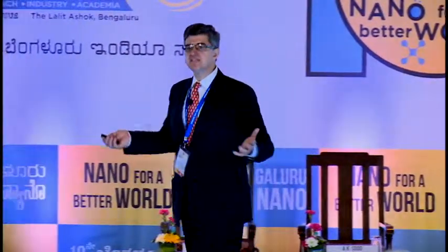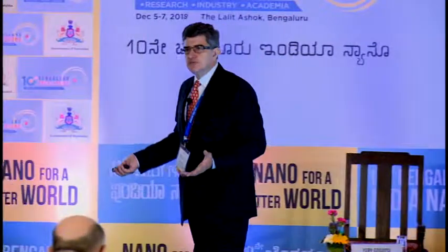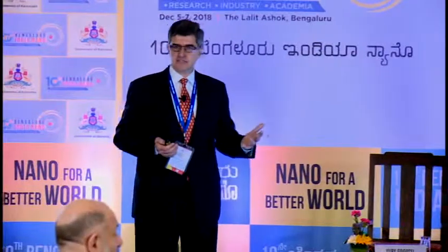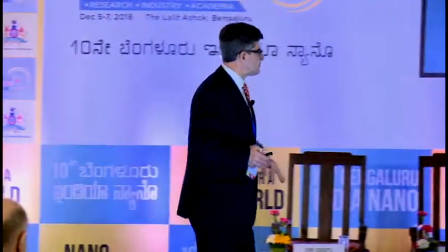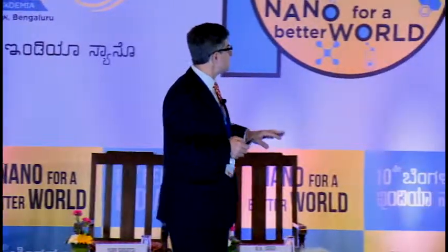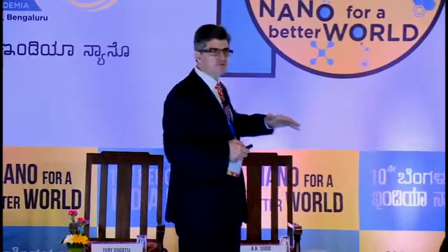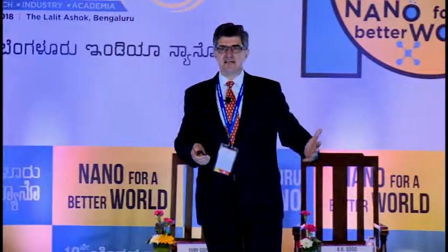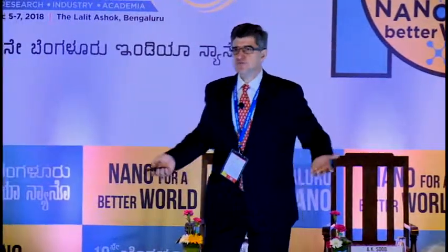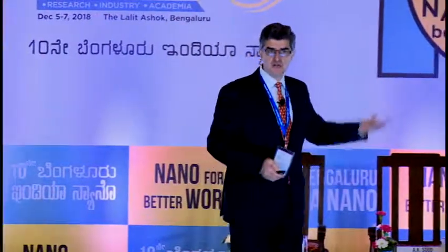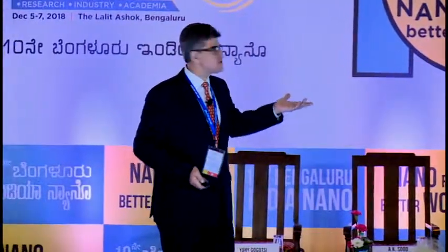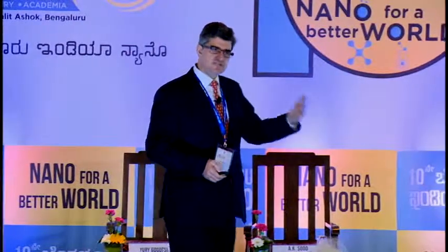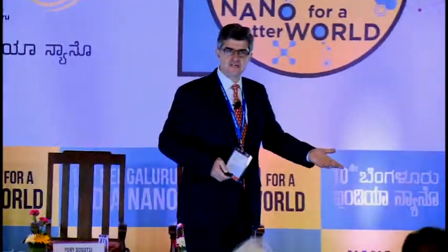And there are, of course, many different challenges. For example, we have a new material. We also need to think about new electrolytes, because electrolytes that are considered to be good by default may not necessarily be the best one. This is an example of work which is still under review in Nature Energy. But it shows that acetonitrile, which is considered a standard supercapacitor electrolyte used with carbon materials and behaving very well, actually shows the worst performance when we use MXene. And propylene carbonate, which is less conductive, with about an order of magnitude lower conductivity, actually shows significantly better performance.